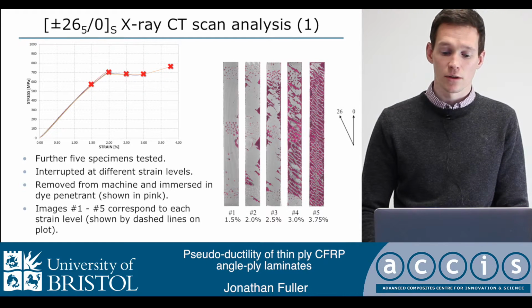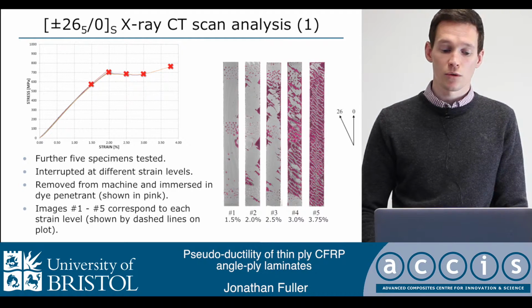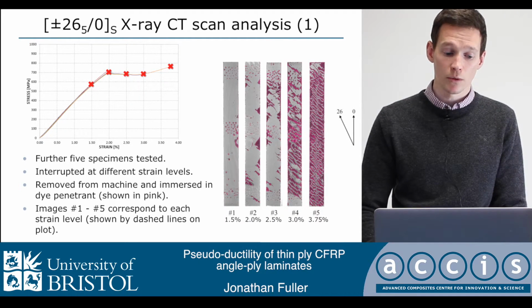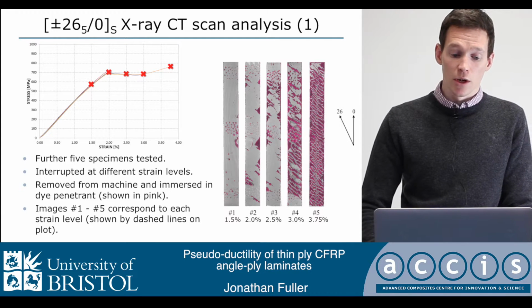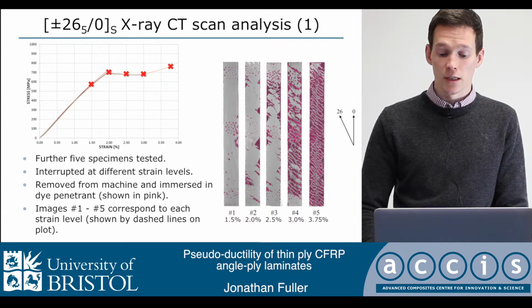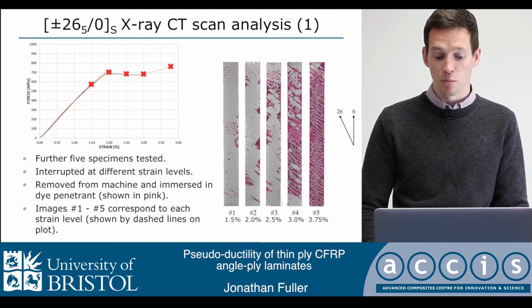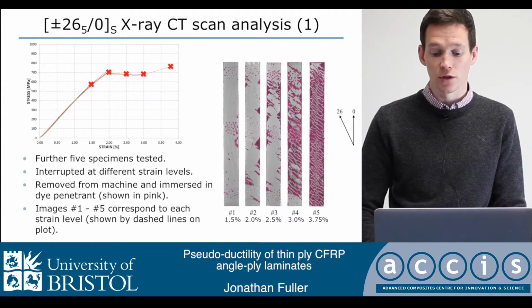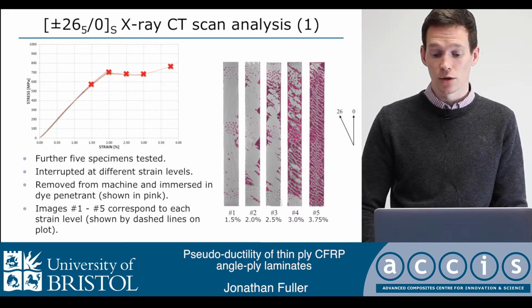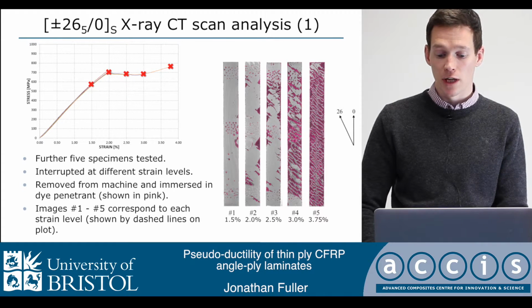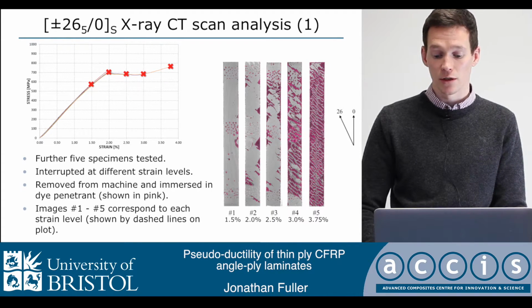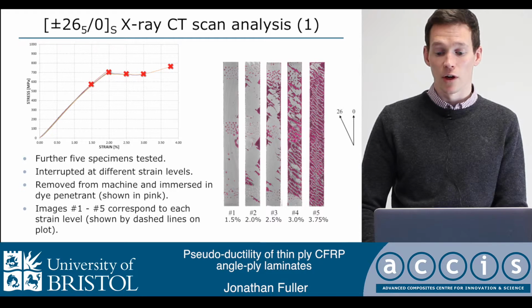So the CT scan on the right-hand side shows 5 specimens which are indicated by the red crosses on the stress strain graph. And these were loaded up to the points indicated, and we can see clearly that the pink, which is the dye penetrant, shows up the damage increasing as the strain increases. So we go from before fragmentation, absolutely no damage, and then gradually that increases through to close to final failure where there is extensive damage.